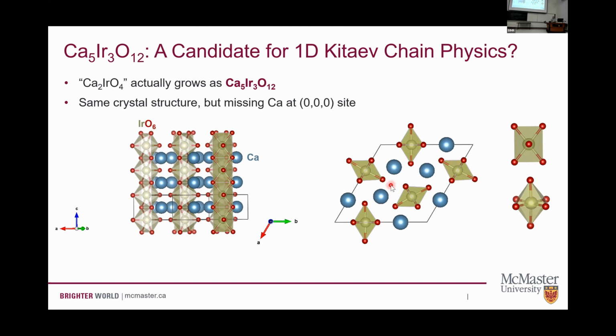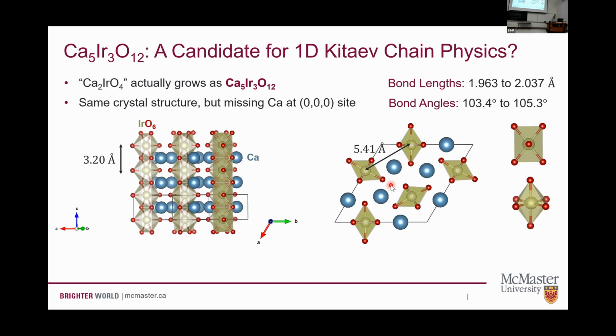We do have some other structural things that might cause a little bit of concern. So these octahedra are not perfectly regular. They're distorted in both directions. So we get quite a range of bond angles here and bond lengths, a little bit away from the 90-degree angle. So we wouldn't expect this perfect cancellation of Heisenberg terms, but it maybe gives us a place where we could find some combined Heisenberg-Kitaev chain physics.